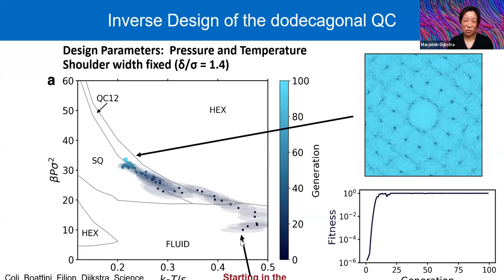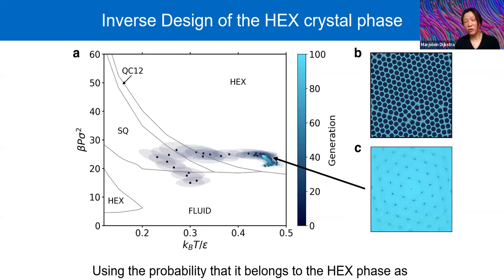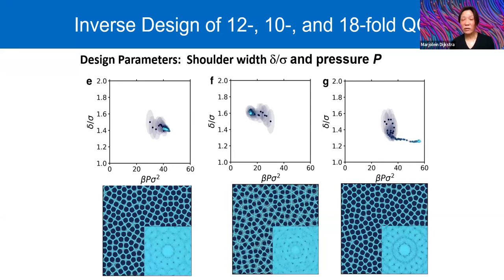So at first, the fitness is extremely low, 10 to the minus 6. So it's very hard to know in which direction it should evolve. But the evolution strategy still knows that it has to go to higher pressures to increase the probability to find the quasicrystal. And within 10 generations, it indeed finds the quasicrystal regime, and the fitness function then has a value of almost 1. We can also use another output node of the convolutional neural network, for instance, that of the hexagonal crystal phase. And also in that case, if we start in the fluid phase, within a few generations, it is able to find the hexagonal phase. We can also use the shoulder width as a design parameter. And also in this case, it is able to find the 12-, the 10-, and the 18-fold quasicrystal.